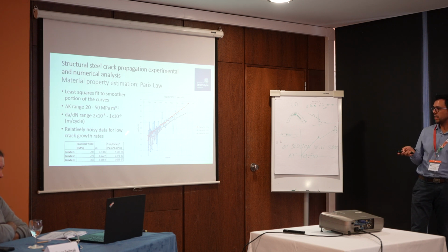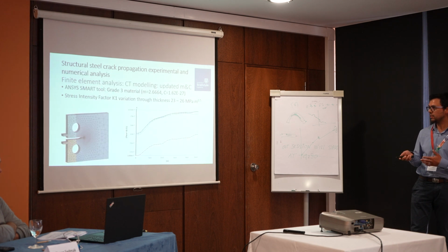Well, we perform the regression in order to get the Paris law parameters, and then this is something that we applied within the ANSYS SMART tool using the coefficients adjusted to calculate the stress intensity factor according to the standard, but as well we use the parameters of the Paris law to perform this analysis.